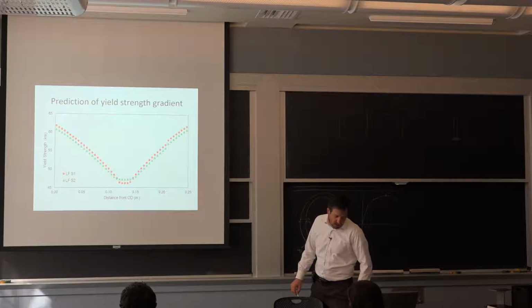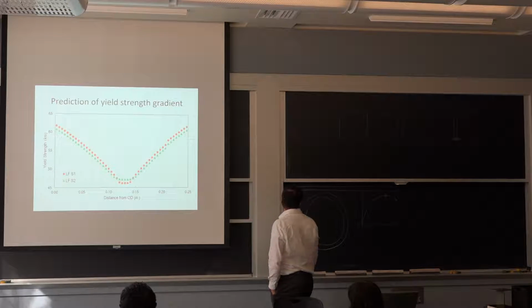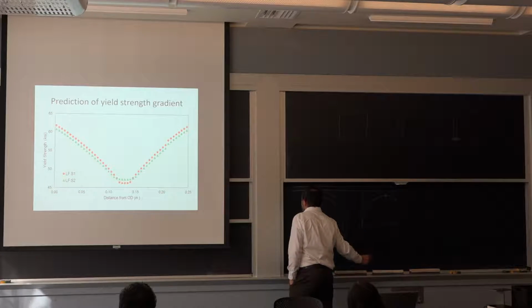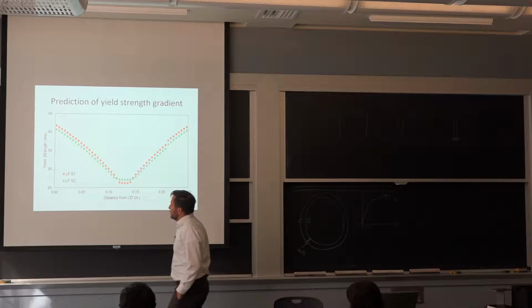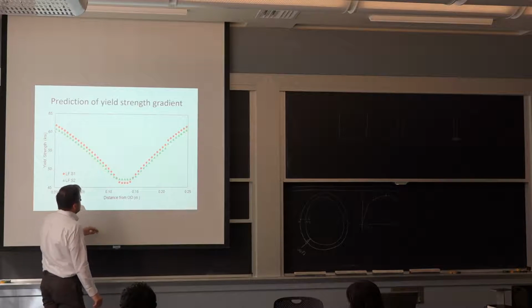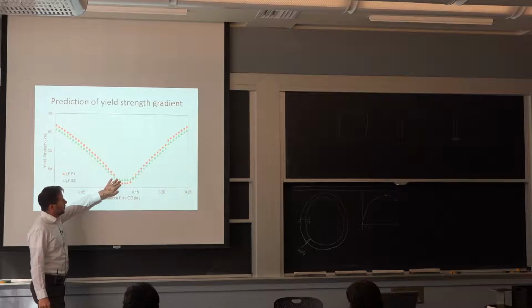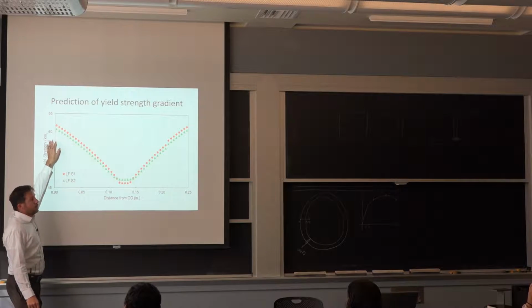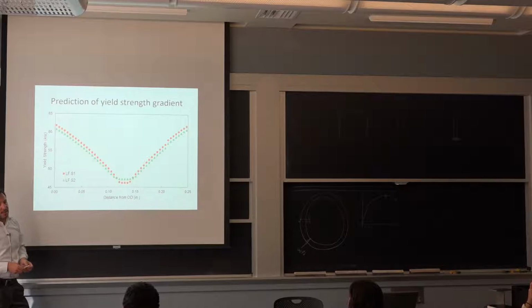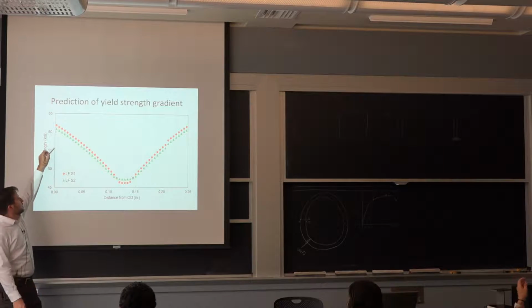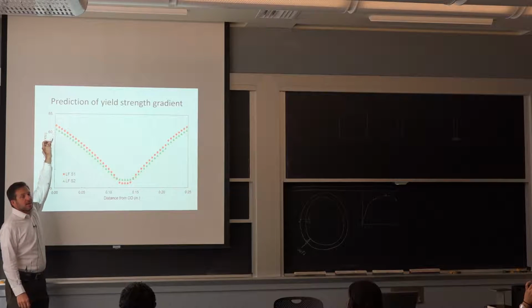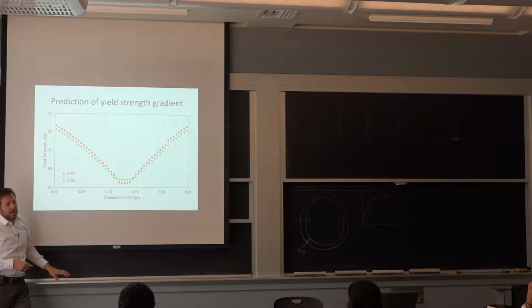The answer is yes, because even if you only have 2.2% strain, essentially the stress strain curve of the material goes from about 46 KSI here all the way to a little bit above 60 KSI on the surface. Now, it turns out that we did run our test on the surface, and we were getting about 59. But it's a prototype; it's not exact.